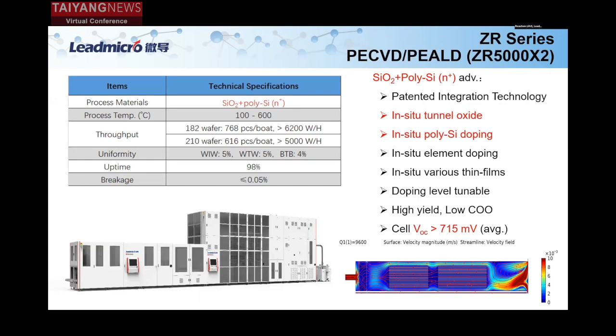With all this advantage, here is the tool we brought to the market, which is probably the first one that integrated the PEALD and PECVD technology together. With this integration, you can do the in-situ tunnel oxide, the in-situ polysilicon doping, the in-situ element doping, and various in-situ thin film depositions. You can switch between PEALD and PECVD methods as you need. Furthermore, the doping level is tunable with the in-situ doping, with high yield and low cost. With all this advantage, it enables our Topcon solar cell VOC greater than 715 millivolts on average.